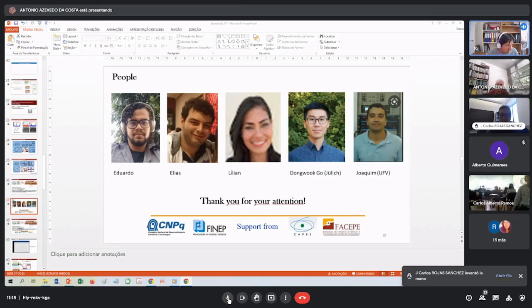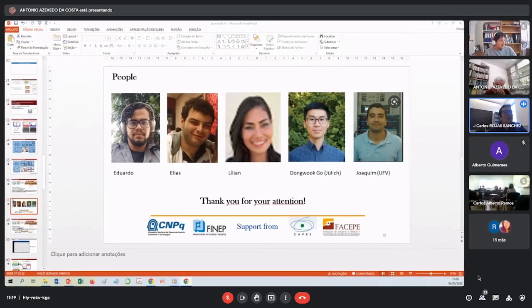Okay, we have a question from Carlos Rojas. Thank you, Antonio. Really nice talk, very didactic. I enjoyed it a lot. I have a question. When I saw one of your results on bismuth selenide and permalloy, and you compare with the same with platinum and tantalum, your results are very clear. You have the same sign as for tantalum. However, it's opposite to what the rest of the groups have reported for bismuth selenide. Usually they report the same as for platinum. Do you have some explanation for this difference?